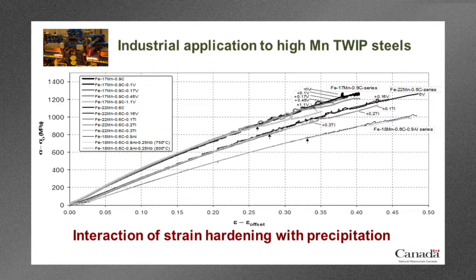And the hardening mechanism of these steels is essentially twinning, twin formation. That's why they're called twinning-induced plasticity steels. So there is some interaction between precipitation and twinning, but it seems to occur mostly at higher strains and mostly when you add higher amounts of microalloying element.